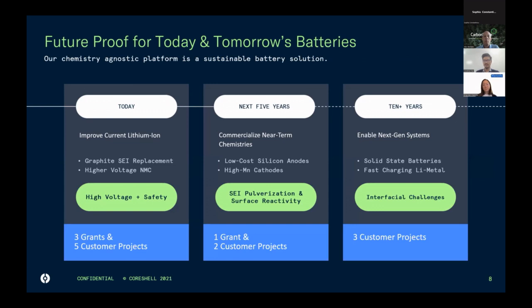As I mentioned, we're doing this across different generations. We've shown efficacy, of course, in current lithium ion by improving voltage range, but we're super excited also to now have enabled some promise in low-cost metallurgical grade silicon anodes at high content, as well as the next generation of high manganese cathodes. And we've started also doing quite a bit of work on enabling faster charging lithium metal, as well as some solid state battery work as well. So interfacial challenges across different generations is really where we focus.